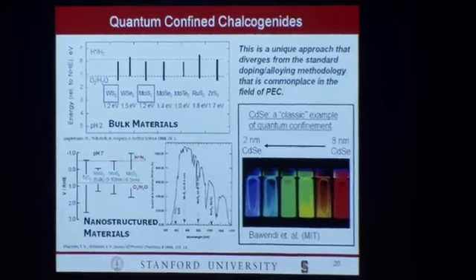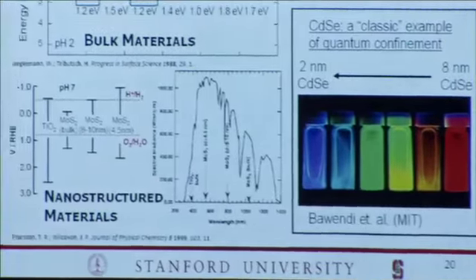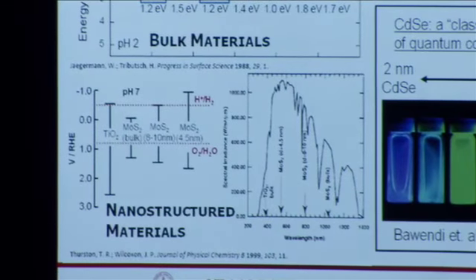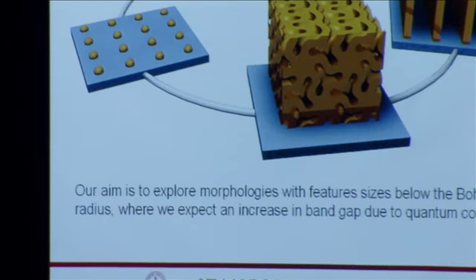It turns out that there was a researcher at Sandia National Labs, Jess Wilcoxon, who had studied quantum confinement in this particular system for the photooxidation of phenols. And what I've done is I've taken one of his images out of his paper and basically drawn the redox potentials for hydrogen and oxygen and shown that, yes, this is where bulk moly sulfide sits, but his 8 to 10 nanometers is quantum confined, as you can see here, just about to straddle the bands. And as you go to 4 to 5 nanometer MoS2, now you've definitely straddled the redox potentials of hydrogen and oxygen. So this tells us that there's promise in this method.